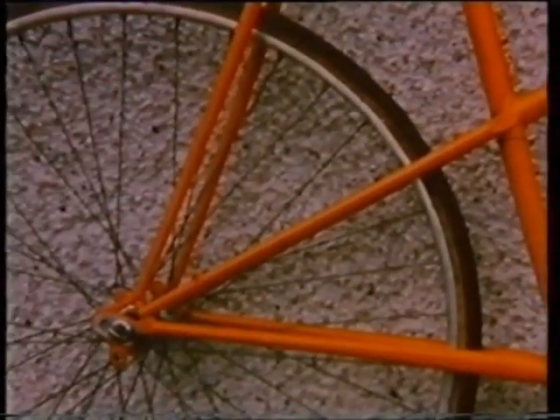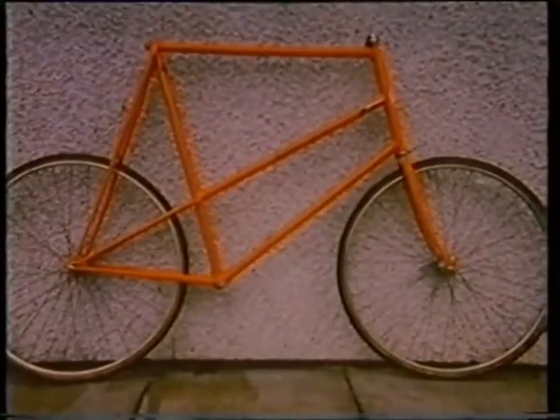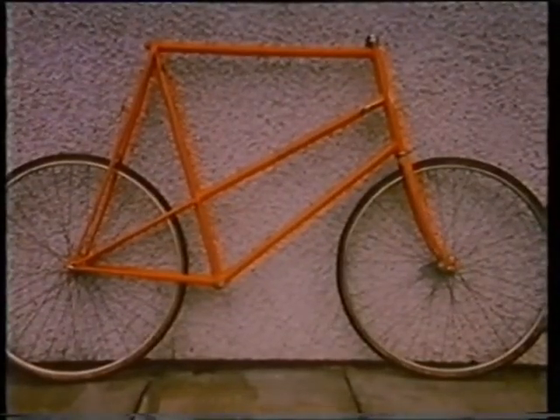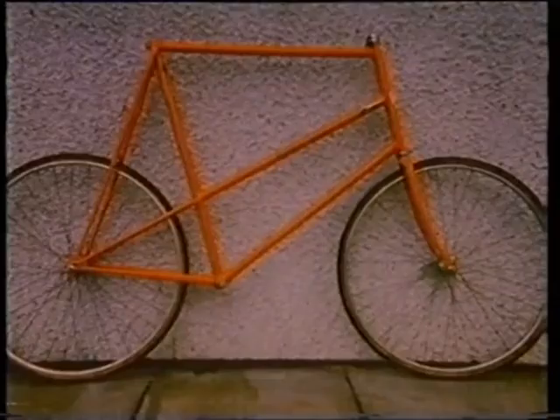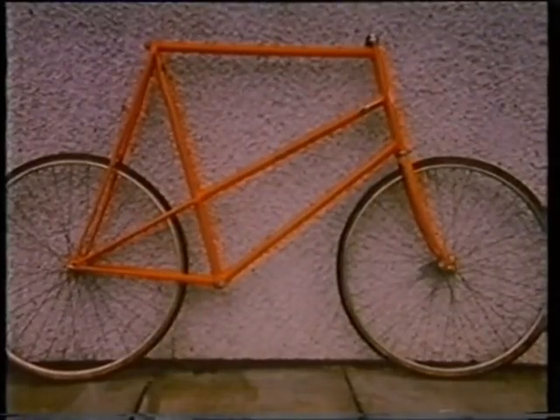Well, we put an extra down tube in first, and we measured the stiffness, and then we added on 2 extra seat stays and measured the stiffness then. And with an overall increase in weight of 15%, we got an increase in stiffness of 30%, which we were quite pleased about. Having gone through your production system, John, how do the material and labour costs of your frame compare?